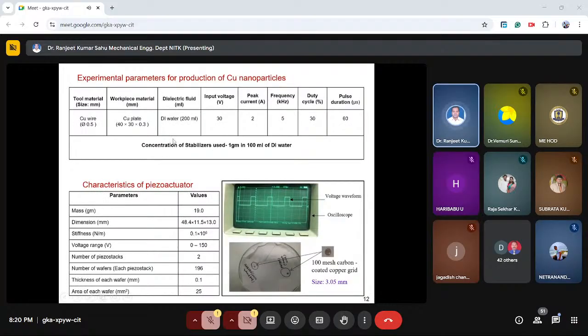You see here, these are the experimental parameters taken for the production of copper nanoparticles, and this is the characteristic of the piezo actuator. This is the voltage waveform obtained on the oscilloscope. These are the carbon coated copper grids placed on the filter paper. Once the colloidal debris is collected in glass vials or test tubes, we drip those colloids on the surface of the carbon coated copper grids and allow them to dry for 2 to 3 hours. Then the dried sample is taken for microscopic and other characterization studies.